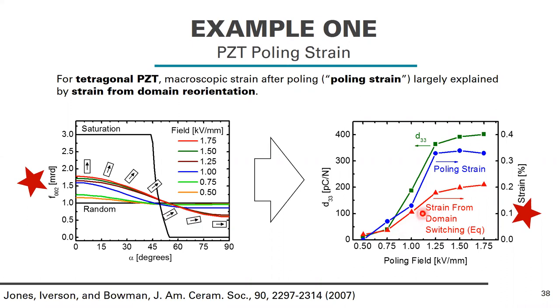So this red curve over here on the right is directly calculated from these pole figures shown over here. Okay? And that well explains the poling strain at low electric fields. And then at high electric fields, you have other effects that also come into play.